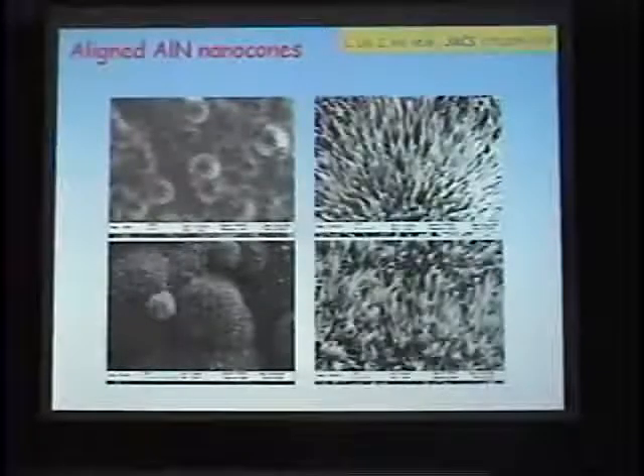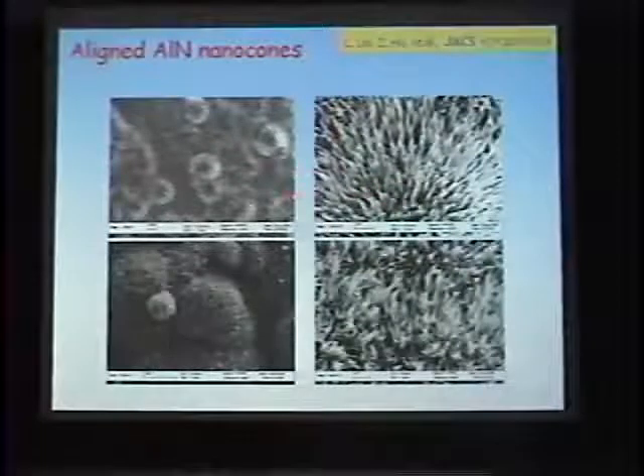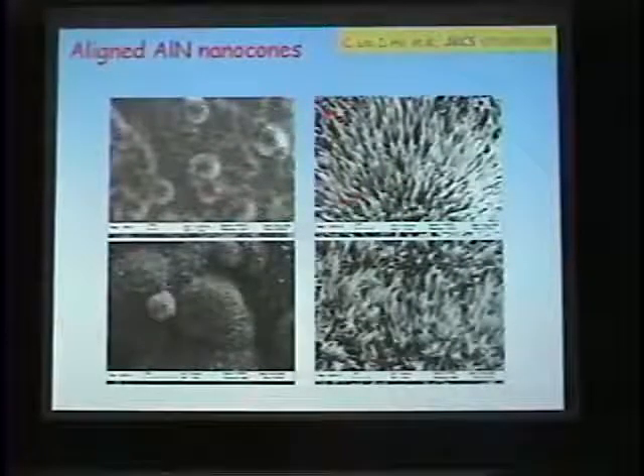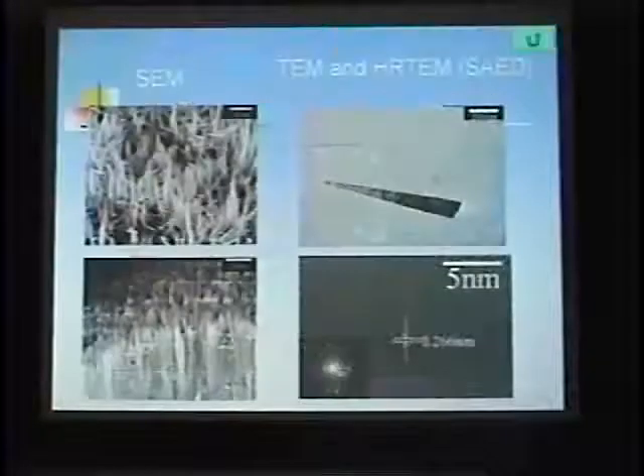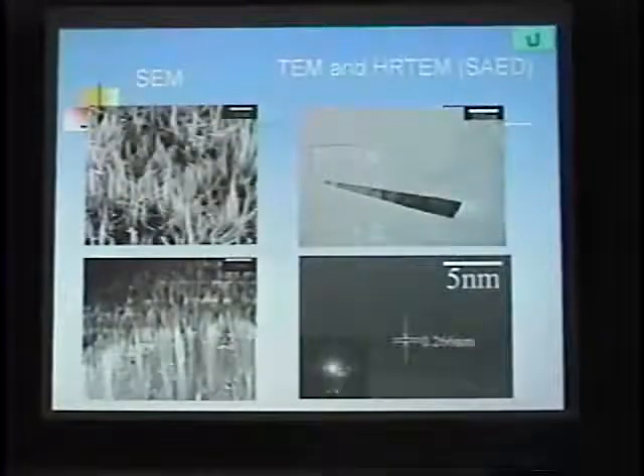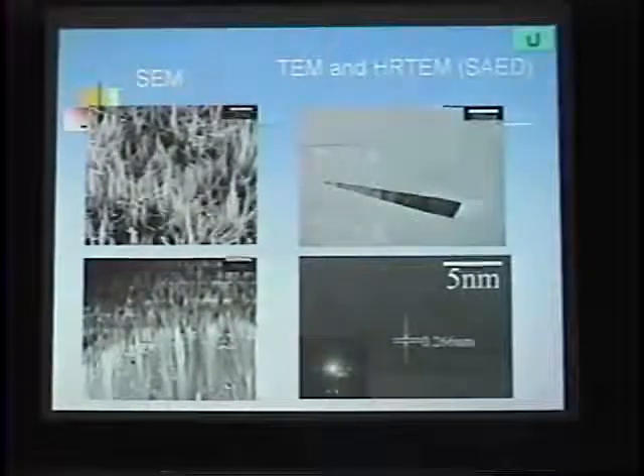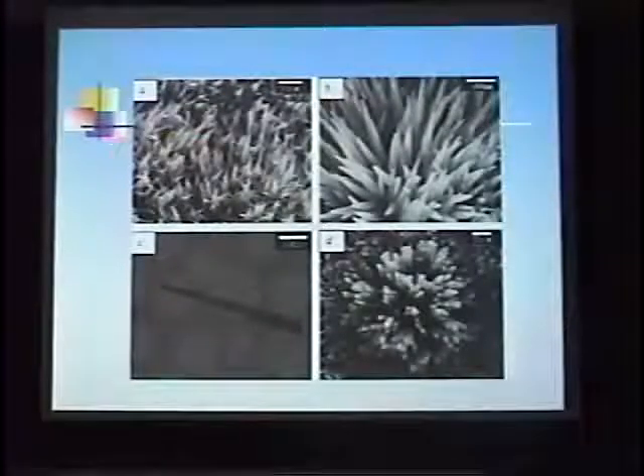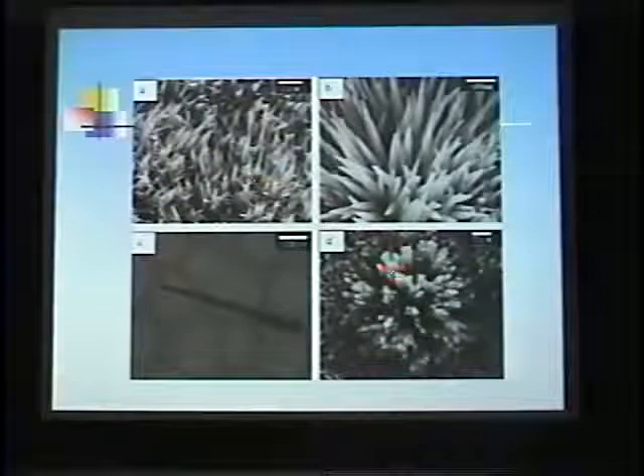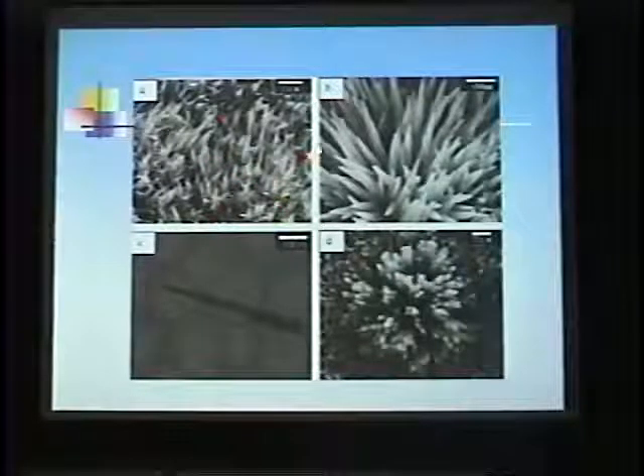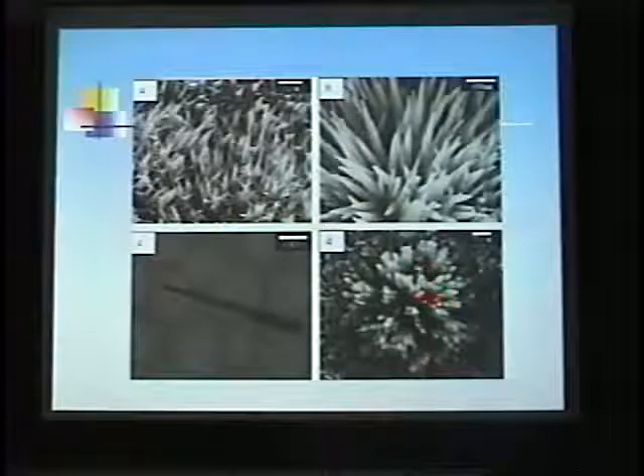We found that in this condition aluminum nitride nanocones could be obtained. This is some morphology detail, looks like this. And if we change the reaction temperature from 700 centigrade to 800 centigrade, the tip will change from nanocone to nanocylinder.